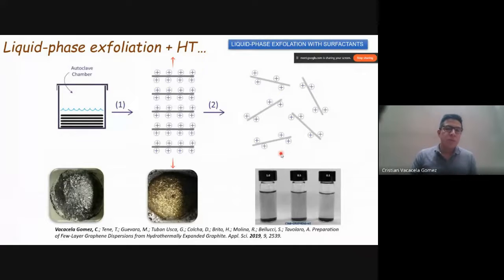If we don't use the hydrothermal expanded graphite, we need more than 7 hours, and in some previous reports, they needed more than 7 days to prepare a high quality graphene or few layer graphene dispersion. If you take that in mind, for a large scale production of graphene, it's not possible to keep the sonicator switched on for the complete process. So for that, we are trying to do something beforehand to reduce the sonication time, and of course keep a good quality and a high concentration of few layer graphene dispersions.